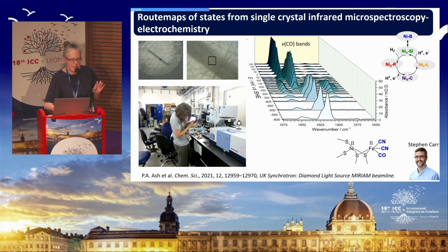And so we're able to start from the most oxidized state of the active site, this oxidized inactive state known as nickel B, and then as we step the potential down, we go through all of those different states relevant to the catalytic cycle that we've seen in solution or on an electrode surface, right down to the reduced nickel R states here.